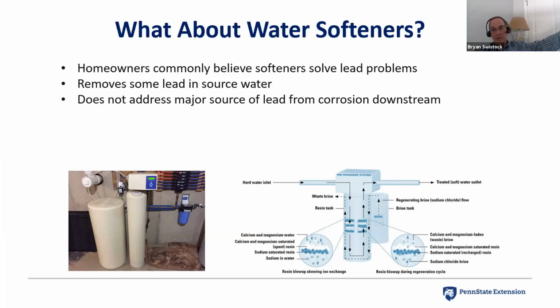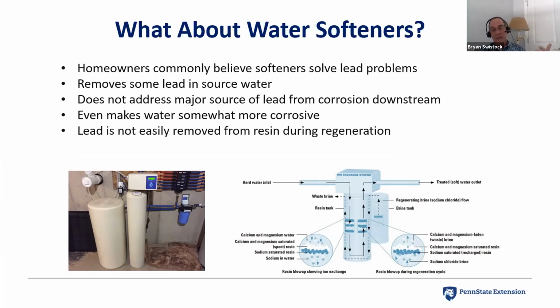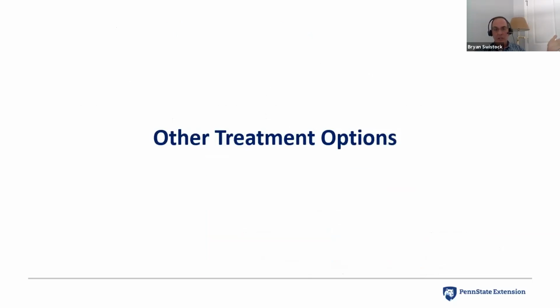And in fact, a softener by definition can make the water slightly more corrosive too. So it's really not going to be the answer to our lead problem, because most of our lead's being generated downstream of that softener anyway. We need to look at other types of devices that can actually remove the lead. And not to mention the fact lead's not easily removed from the resin once it attaches either. So it's definitely not the ideal solution, not even a preferable solution at all.